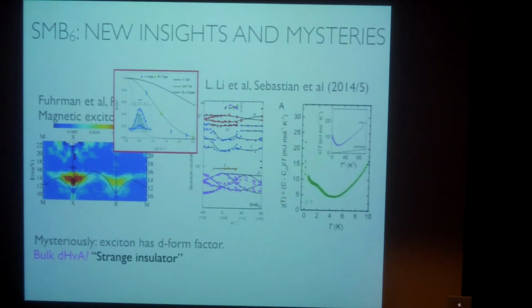And one indication that something weird is going on is that the specific heat capacity has a large linear component that never goes away at low temperatures. It's been there for 30 years. You can grind the system up, and it shows the same linear specific heat capacity. And so there's a large density of low-lying states invisible to the neutrons.